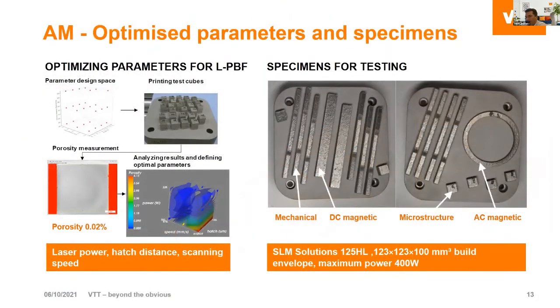Okay, then when we have the powder ready, the next phase is the actual additive manufacturing and finding the optimal parameters for the additive manufacturing. And it's pretty much connected to what we are looking for. The most typical case in additive manufacturing parameter optimization is looking at the porosity of the material. And of course, the porosity is also connected to the mechanical properties and partly also the magnetic properties in our case. But if you have something like 1% porosity, that could also be beneficial for the magnetic properties.